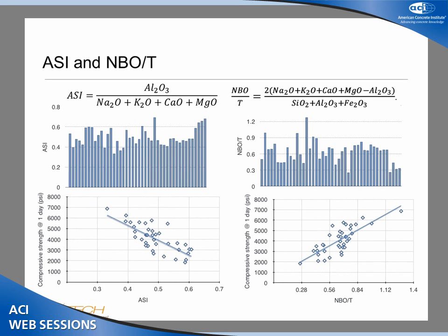So when we plot this with the compressive strength, this is what we get. So for example, here an alumina saturation index of 1 would be that all the aluminum is fully balanced and your network is looking more like this, right? There's more polymerization in the network and it's a more stable network. So once your network modifiers start to go up, or the amount of calcium usually is what starts to go up, then you have a network that looks more like this one, a more fragile glass, a more disrupted glass that is more reactive. And we can see that the compressive strength is actually going up as your alumina saturation index numbers drop.